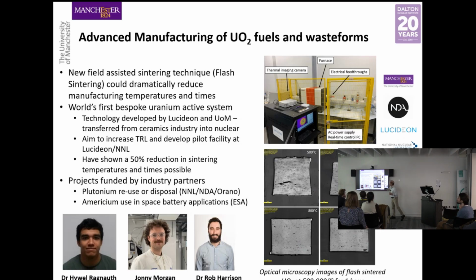And actually, final slide, I think we have also been looking at how we might manufacture not just UO2 fuels, but waste forms, material for incorporating plutonium into that could survive for very long periods of time, using very novel technologies. So I talked about the sintering process for manufacturing nuclear fuel. At the moment, industrially, we do what we call pressureless sintering. So effectively, we take our uranium dioxide powder, we press it into pellets, and then we bake it at very high temperatures, about 1,750 degrees C, for 6 or 7 hours in flowing hydrogen, in other words, in a reducing environment.